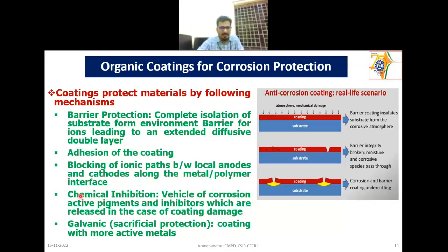Then another thing is chemical inhibition. That means we add some kind of inhibitor molecules in the coating so that they will stop the corrosion. Then another one is galvanic protection, coating with more active metals. We know that for galvanized iron, we use zinc. Zinc is more active, so zinc will undergo corrosion, protecting the underlying ferrous metal substrate. So these are the major ways a coating protects underlying metal substrates from corrosion.